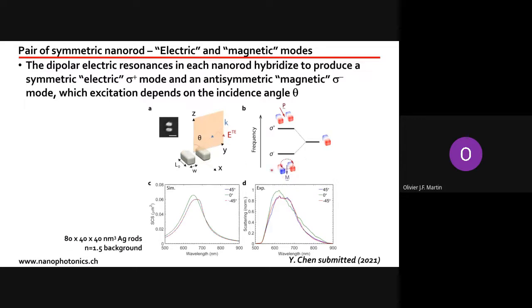As a consequence, you see the delay, and the blue and the red show the polarization charges. Because it's a metal, it has a lot of free electrons, and these free electrons can all go on one side, where it would become blue. Because they have all gone on one side, the other side of the particle will have a deficit in electrons, and it will appear positively charged, so say in red. So this mode looks like a small current loop. So it looks like a magnetic mode. This mode, on the other hand, is typical of an electric dipole resonance.